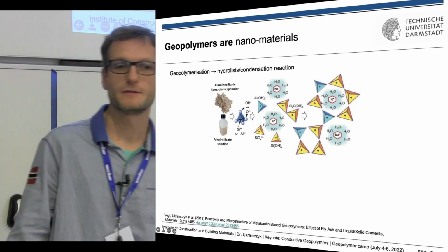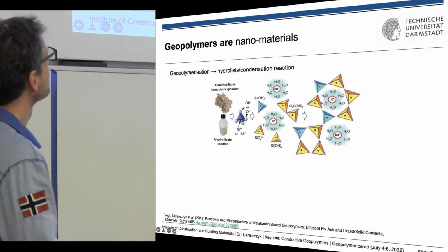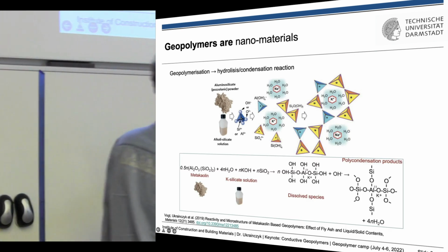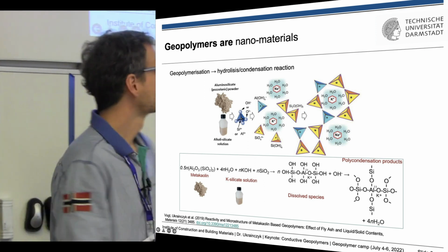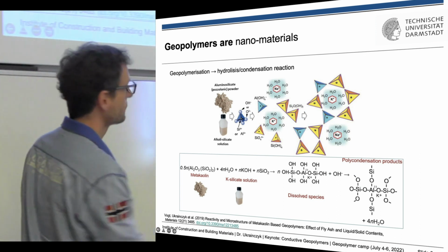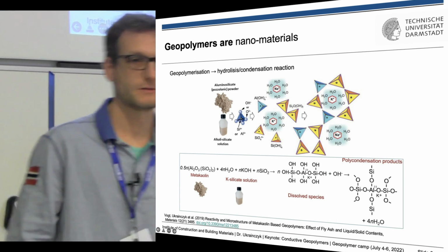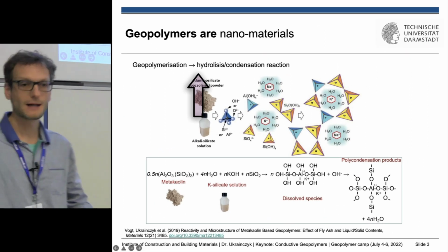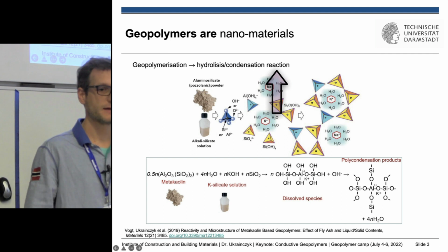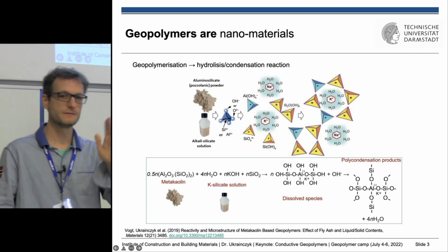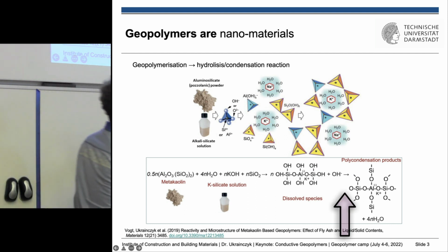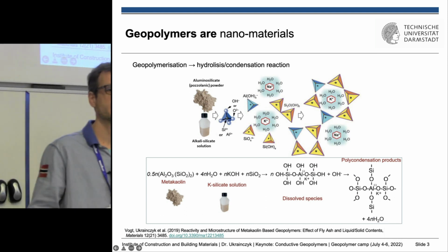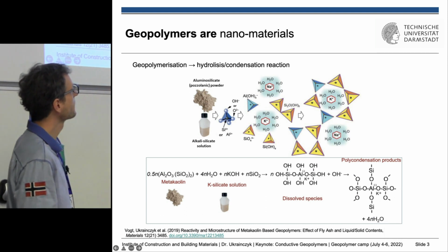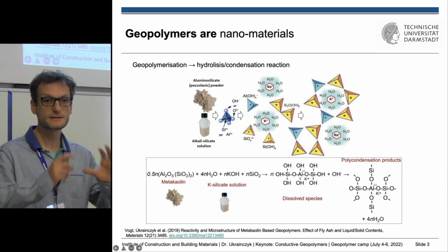So we heard a lot about this. Especially I would just mention that here we have actually a reversible reaction. So first we dissolve, depolymerize, what we heard. It's also called hydrolysis and alkalination, because the alkalis attack these oxygens which then can depolymerize. But later we have this polycondensation reaction. So we create oligomers in solutions, and later they polycondensate further, and we have the making of these geopolymer